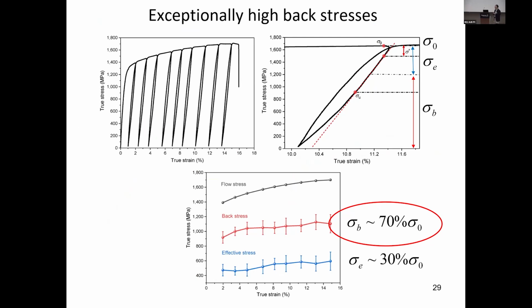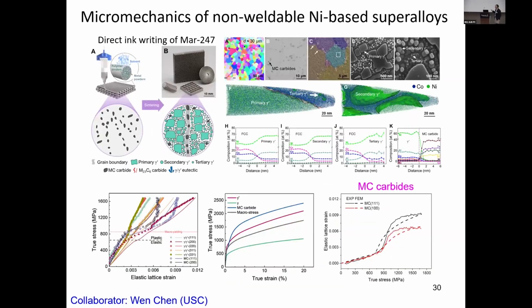So again, we also study the detailed internal stress evolution within this complex dual-phase nanostructure in the bulk samples, right? One important takeaway is that back stress accounts for about 70% of the total flow stress. So the majority of the stress increase arises from the nanostructures and also the associated directional back stress effect.